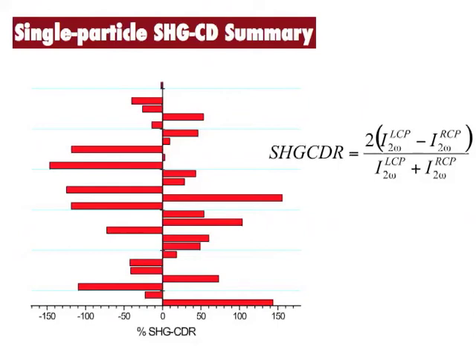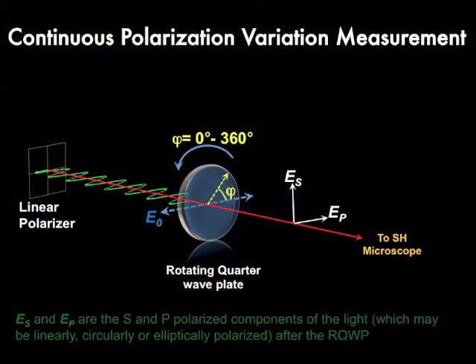Something implicit in this circular dichroism response is that there must be a contribution from magnetic dipoles to the nonlinear optical signal. As we describe in the perspective, the technique of continuous polarization variation, or CPV, measurements can be used to quantify the relative contributions from electric and magnetic dipoles to the plasmon response. CPV measurements are achieved by systematically changing the polarization state of femtosecond laser light prior to nonlinear optical measurements.